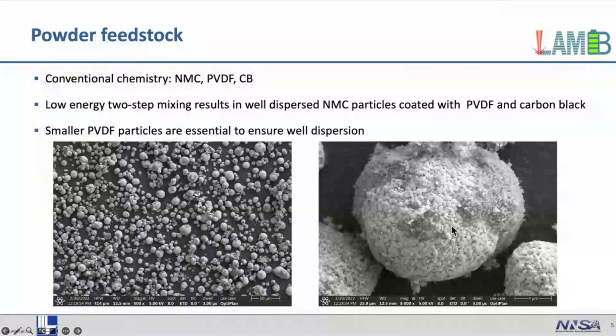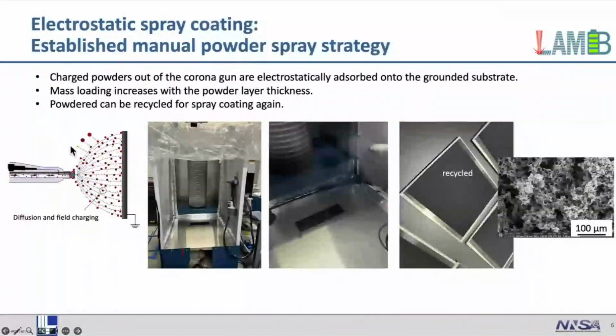So starting from those mixed powders, we apply this electrostatic spray coating where there is a high voltage electrode at the end of the nozzle. When the powders come out from the nozzle, those particles are charged with the electric field and then deposited onto the grounded substrate. And here is how it works.